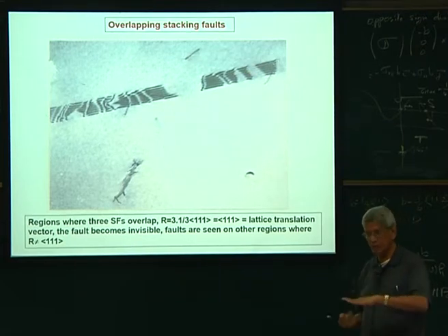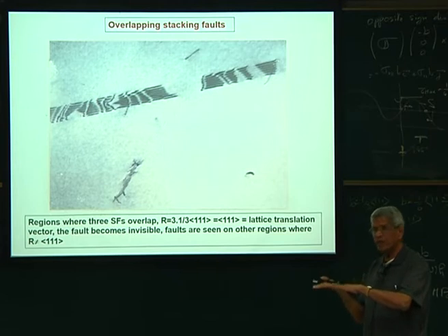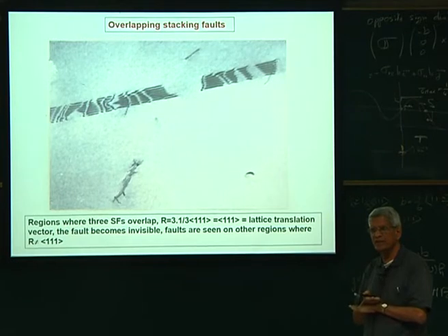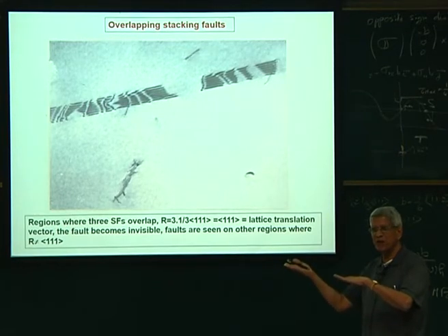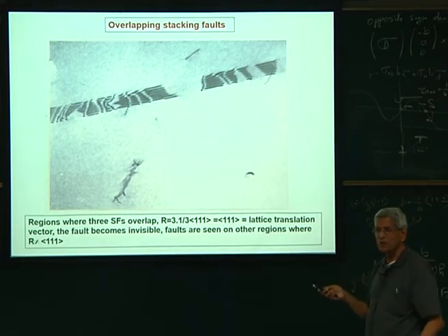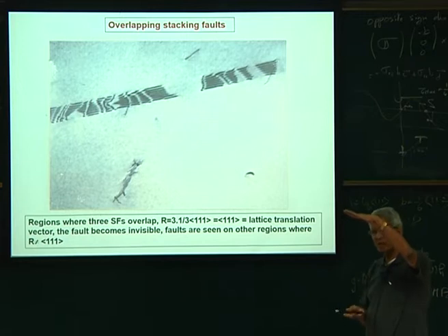What essentially happens is that one layer of fault is there, then when the next layer of fault comes, also a fringe is going to be there. When the third layer, the same fault, is created, ABC if I move it all, now it has become like a normal stacking sequence. So if three faults are overlapping, then that region appears as a normal region.